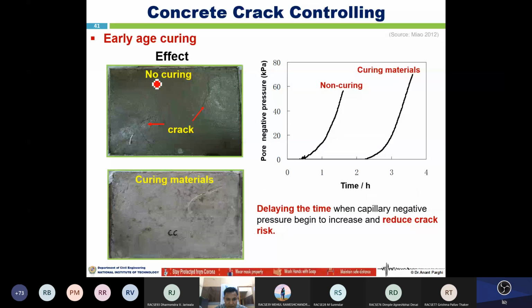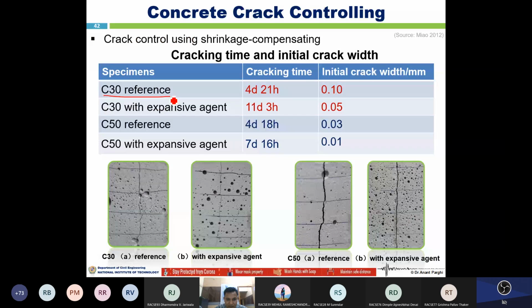With early age curing, in this particular area with no curing, cracks are going to develop, right? This kind of crack is going to develop, but if you apply proper curing, this is the curing material here. Non-curing here, these are the curing material. Here the pore negative pressure will be increasing, which can delay the cracking. If you are using 30 megapascal concrete with 4-day curing of 21 hours, the initial crack width will be 0.10 millimeters. If you apply 7-day curing, the crack width will be 0.01. This way we can control the cracking.